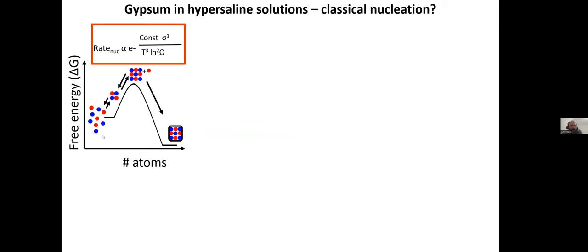I already showed you this graph you see here of the conceptualization of the classical nucleation theory. And above it, I added the equation that gives the rate of nucleation according to the theory. So basically the rate is proportional to e to the minus of different constants. Sigma to the third is an interfacial tension that for a single crystal, gypsum in a single brine, would also be constant. It doesn't change over time. The temperature, which is controlled in my experiment, is also a constant, and then the natural logarithm of the oversaturation.